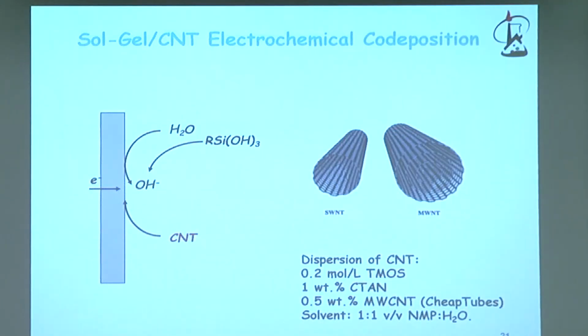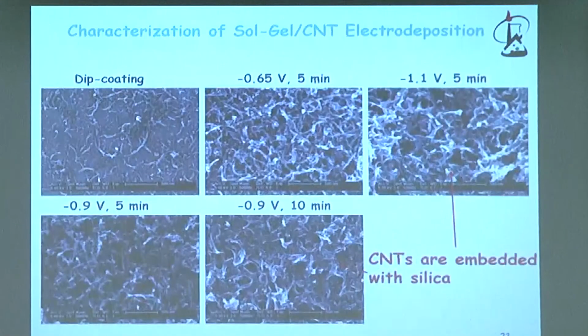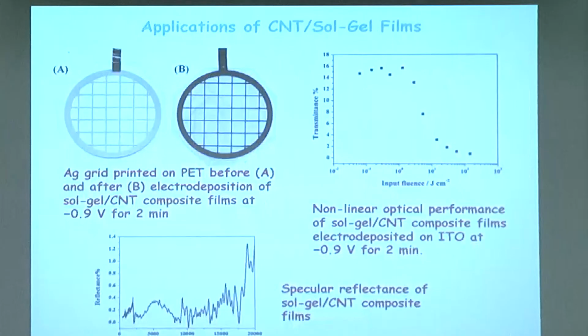You make a dispersion of carbon nanotubes. Inside the solution, you add a sol-gel monomer. This is the tetramethoxysilane and so on. You apply a potential, and you get very nice deposition, as you can see here. Here, you get actually a deposition which contains the carbon nanotubes, the rate of deposition, and also the ratio between the sol-gel and the carbon nanotubes depends very much on the potential. You can see that the deposition does not take a long time, and then you can actually analyze it and so on.